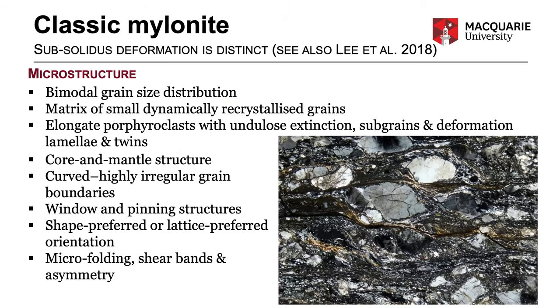A second take-home message is that the high strain zones that we studied here in New Zealand have very different microstructure compared to a classic mylonite, which is shown here in this picture that I've just copied from the web. I won't go through all the features listed, but ask you to contrast this photomicrograph of a typical, you know, 500 degrees Celsius mylonite, with a microstructure in the shear zones of our study on the next slide.